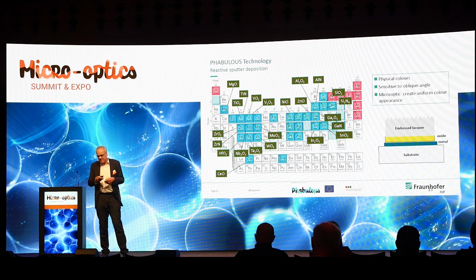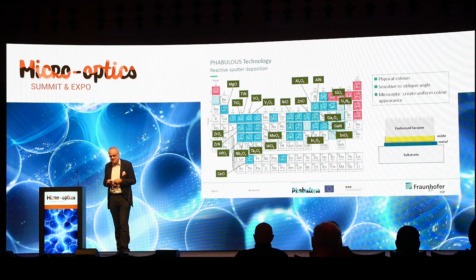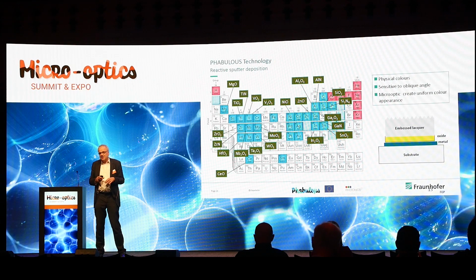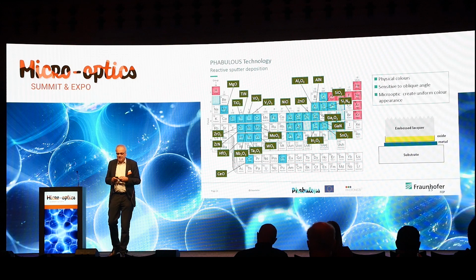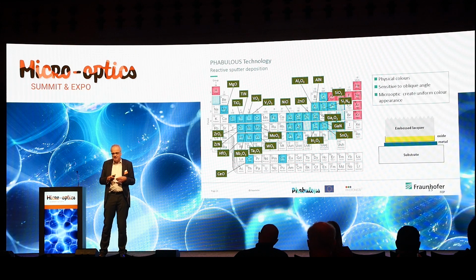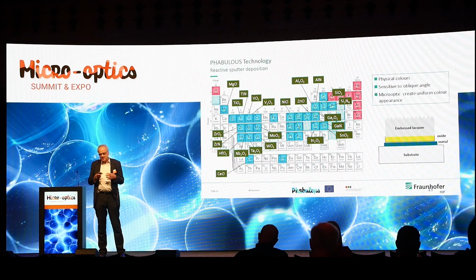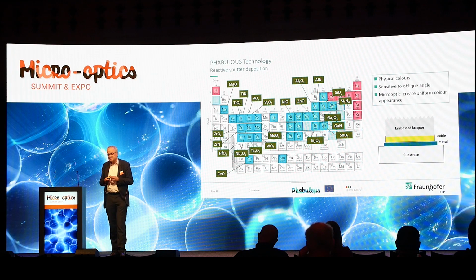So this can be achieved with layer stacks as we have shown here on the right. And it's very important to get them combined with micro-optics, because these physical colors, they have the property of a color shift when you are tilting them. And that's not every time that what you want to have. And with micro-optics, you can mitigate this property so that you finally can tune between the exact color and also the color appearance in the final application.